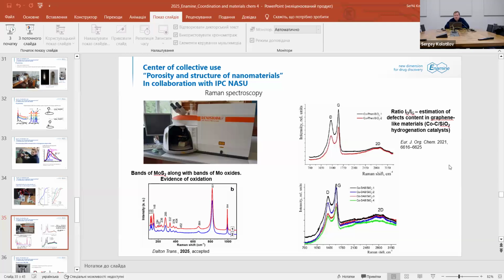Two representative examples. Here on the left, you can see Raman spectrum of molybdenum disulfide. So unexpectedly, we found that there were a lot of bands which were not bands of molybdenum disulfide, and it appears that it was oxidized molybdenum sulfide, even molybdenum oxides, and it could explain some effects which we observed. And also we can make characterization of materials which have carbon, like graphene-like materials, by measurement, for example, of ratio of intensities of different bands. We can make conclusions about quantity of defects and so on.